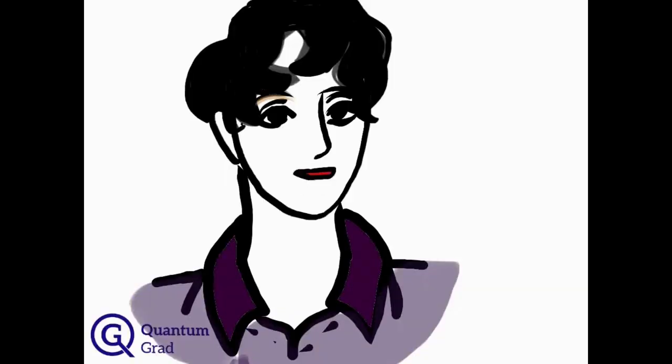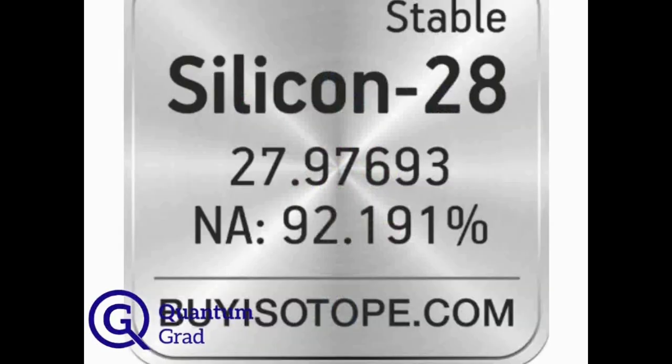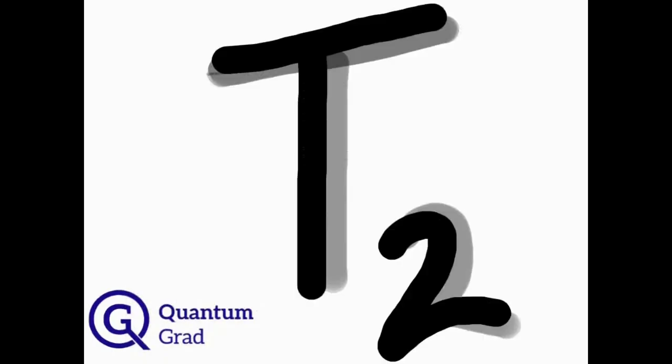How do we tackle this problem? Simply change your quantum material. Thus, we now use silicon because more than 95% of naturally occurring silicon carries no nuclear spins. We use the isotope silicon-28 because the nuclear spins can largely be eliminated using this isotope. Using this isotope, we can significantly increase the time taken by the qubit to randomize its phase, that is, the randomization time.